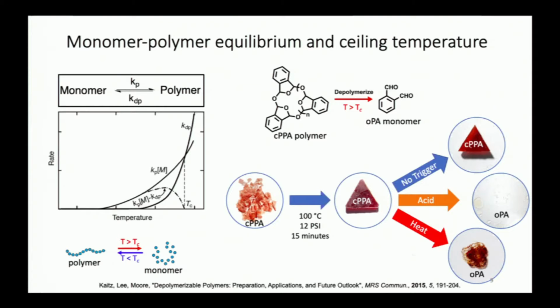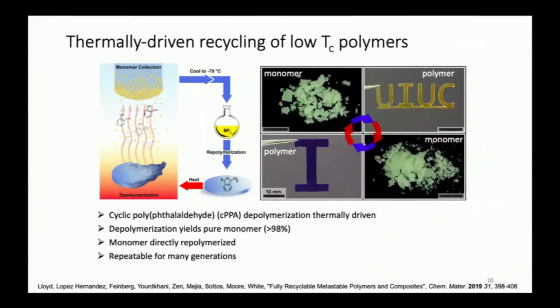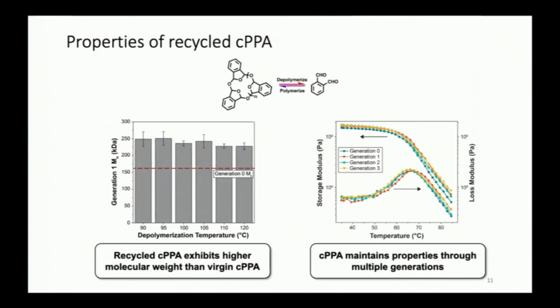We've learned to manipulate and handle this and process it, and it actually is quite a useful engineering thermoplastic, meaning that it has high performance characteristics that you would like. And then it is possible to simply put it through a cycle like you see here, taking the material, heating it up, recovering quite effectively that monomer, and then repolymerizing it back. And you can do this for many cycles; we've certainly been able to show that there isn't any compromise.